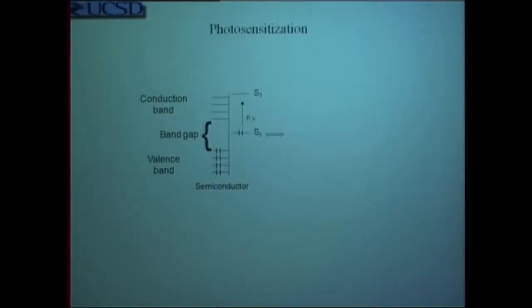So how could you address, first of all, this match with the solar spectrum? Well, one way is to recognize that in addition to doing band gap irradiation, as I've shown here, the substrate shown at the right, S1, when exposed to light, generates an excited state which has a different electron distribution. It will be dominated by the absorption of light by the sensitizer, S, which is attached, rather than the material itself. And there's been a great deal of work understanding that kind of sensitization.